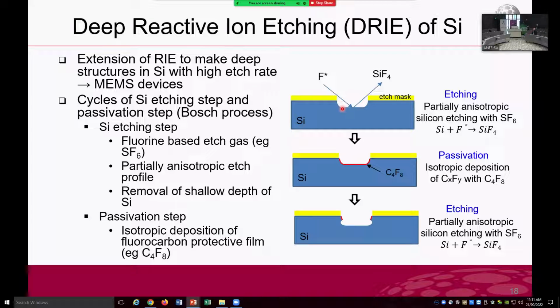It's not desirable. So to overcome this problem, in the second step, we introduce a passivation layer, which consists of a coating by C4F8 gas, a fluorocarbon gas. After this passivation step, in the next etching step, this fluorocarbon protective layer on the horizontal surface is removed because of the vertically directed ion bombardment, and the coating on the sidewall remains intact. After removing this coating, another silicon etching proceeds. By repeating this etching and passivation step, you can achieve globally vertical etch profiles.